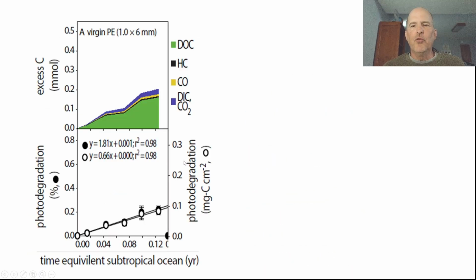Well, unfortunately, the axes on the bottom and the axis on the top don't seem to be presenting the same information. I have to work from the data on the top because that's the one that breaks the composition of the degradation products out into different types. So for me to do the fit that includes a CO2 escape, I have to know what the relative amounts of everything are. So I have to work from the top, but the top doesn't correspond to the bottom unless I'm totally missing something. Even if you just look at a single point, this one's about 0.2 millimoles.